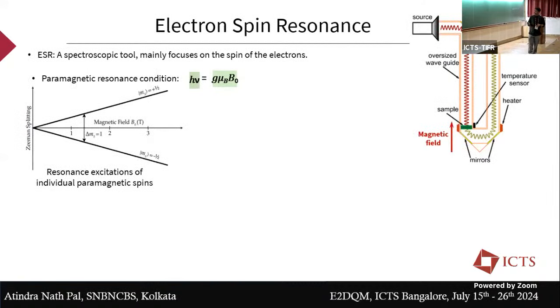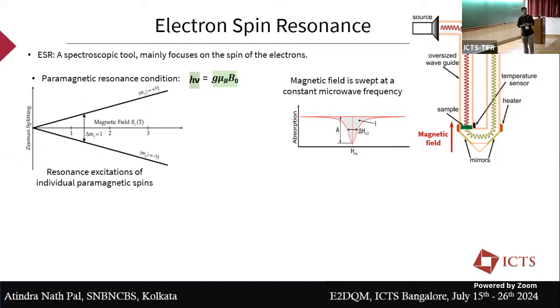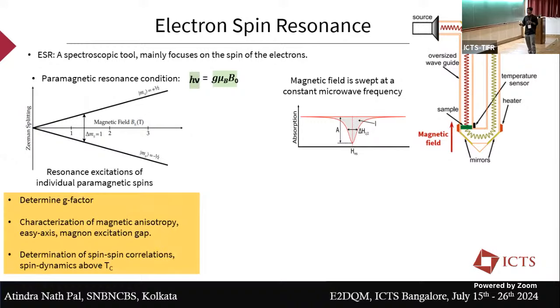So under this MOU, my student Riju went to Dresden for 6 months, and he did this ESR experiment with Alexei Alfonsov and Vladislav Kataev. So, a brief introduction to ESR. I think most of you have done ESR experiments in the masters, where for a paramagnetic sample you apply a magnetic field and create a Zeeman gap, and as you sweep the magnetic field, keeping the microwave frequency constant, you will see a resonance. Using the ESR technique, you can of course determine the g factor, characterize the magnetization anisotropy, easy axis, and magnon gap, all these things you can determine.